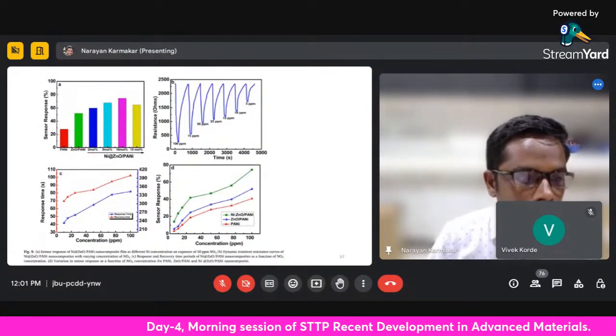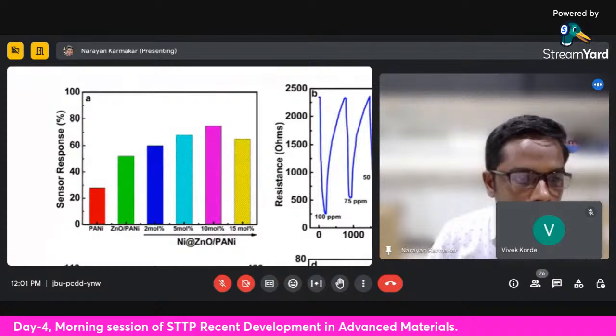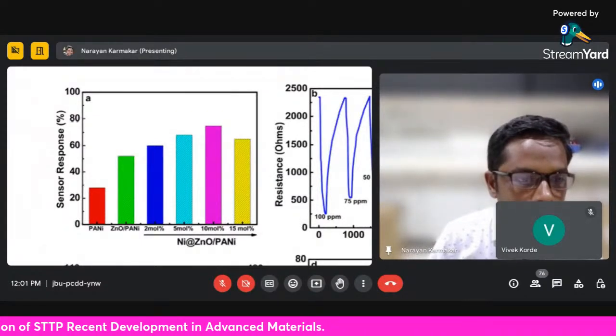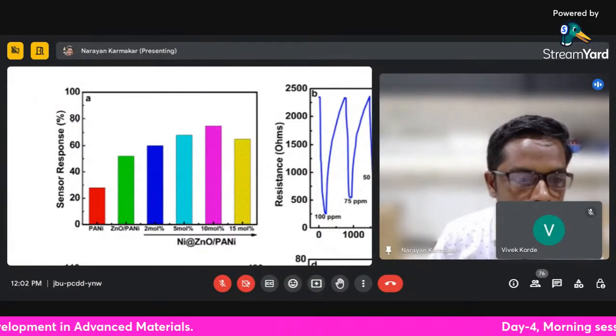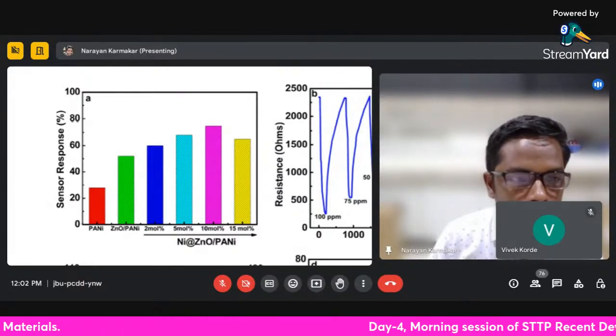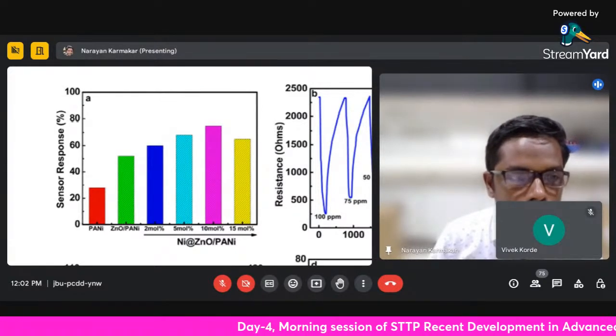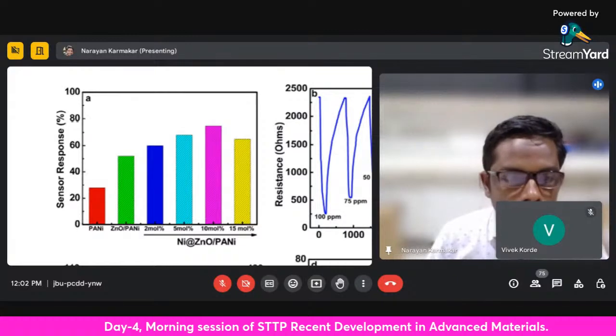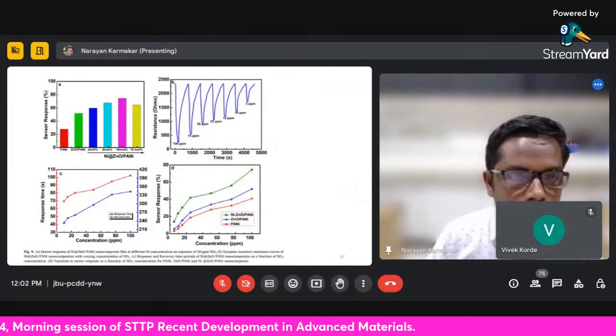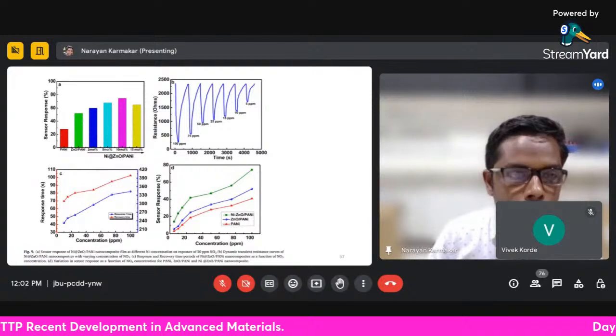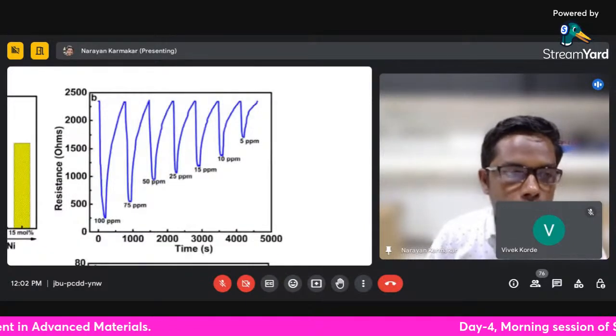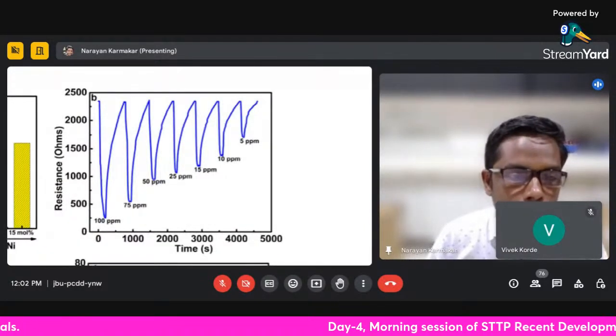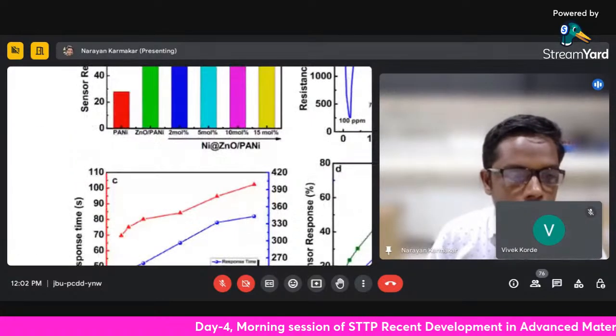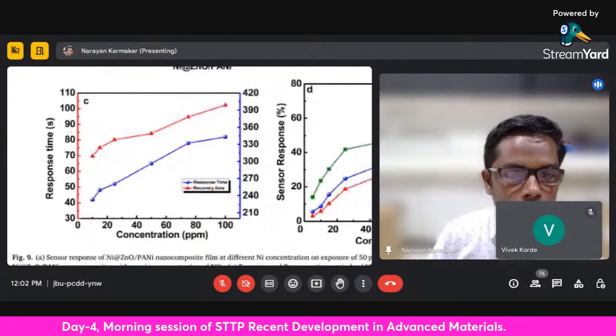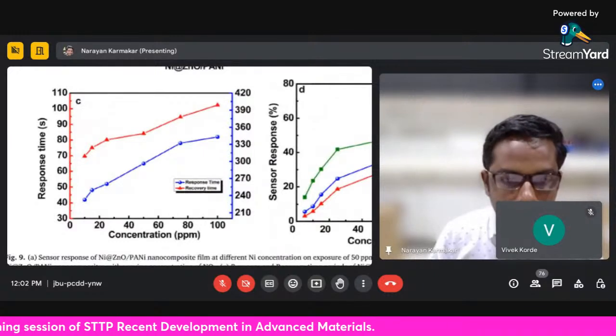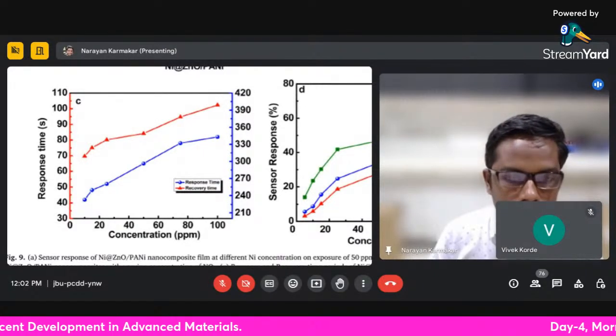We can see for different combinations: for PANI, what is the response? For zinc oxide PANI, what is the response? And for different doping levels of 2%, 5%, 10%, 15%, we saw that the optimum concentration was about 10%, giving a maximum response. We again studied the variation for different gases, and for 5 ppm it was much more sensitive compared to the other composites. We saw the response time and recovery time improved a lot for this kind of gas sensor.